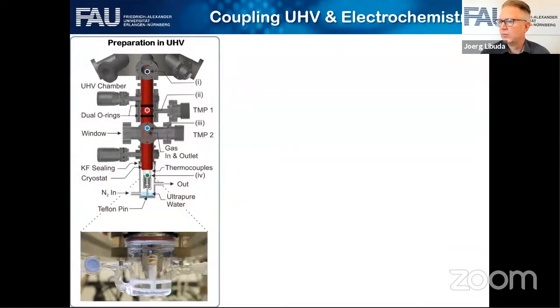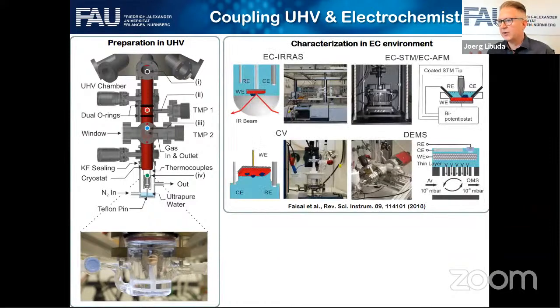So to give you a better understanding, what's the technology behind? This is the system that you saw, and this is how it's built up. There's a vacuum part, there's a liquid part down here, you can move the sample, there's a lock. And then the single crystal is clamped here and will be disconnected and brought into the electrolyte. And the good thing with this approach is that it's quite universal. We use this preparation technique, for instance, to do electrochemical infrared spectroscopy, mass spectrometry, cyclic voltammetry, and electrochemical STM. So it's quite universal.